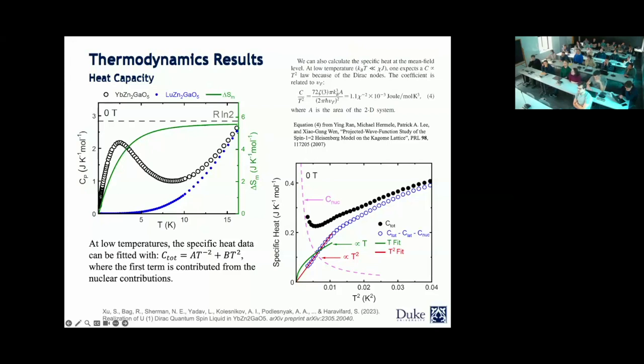So this is specific heat as a function of T², and there's a reason for that. If you look at the fit for the linear, the power law fit that would give us a linear behavior, it doesn't fit really well. But in T², it actually shows a very nice fit down to the low temperatures at about 120 millikelvin. So this is actually an important outcome of this analysis.